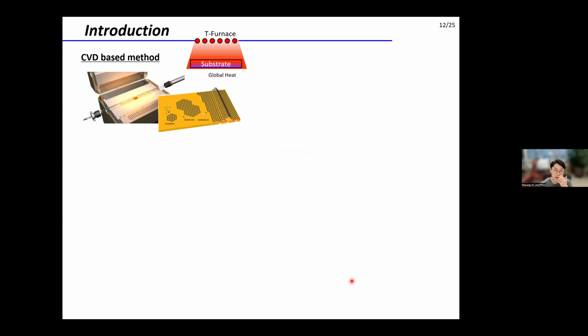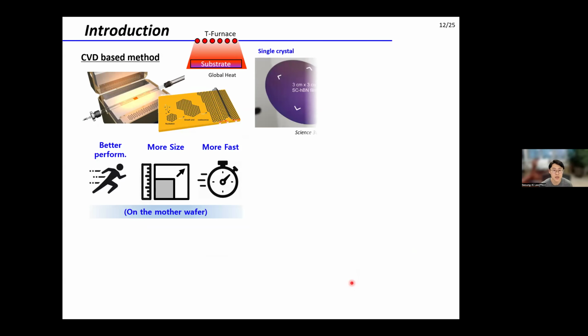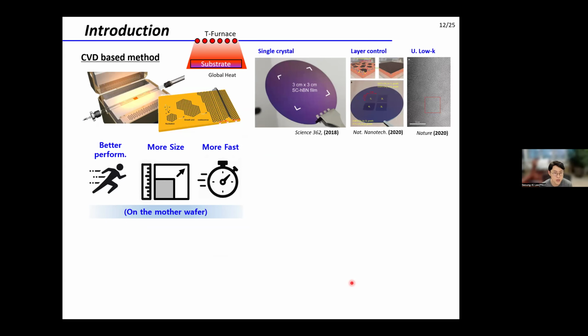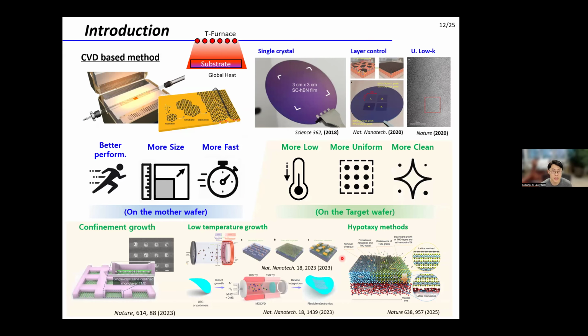The development of CVD technology has been rapid and remarkable. Before the 2000s, researchers focused on large-area synthesis of high-quality 2D materials on a mother wafer. However, due to the need for the transfer process, attention has shifted toward direct synthesis on the target substrate. In particular, low-temperature and clean processes are gaining increased interest. Recent studies have demonstrated the synthesis of 2D materials below 400 Celsius, enabling integration with CMOS devices and flexible substrates. Despite this advance, one limitation remains, that is the narrow synthesis window of this approach. In this region, reliably achieving high-quality material is still challenging for many researchers.